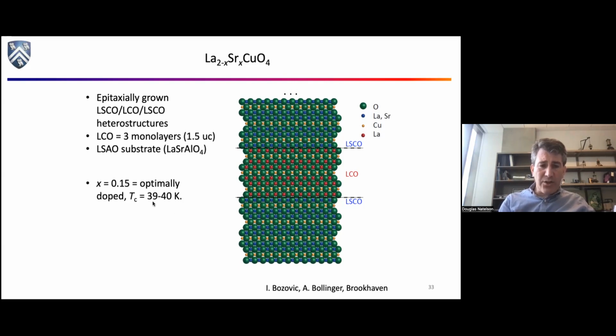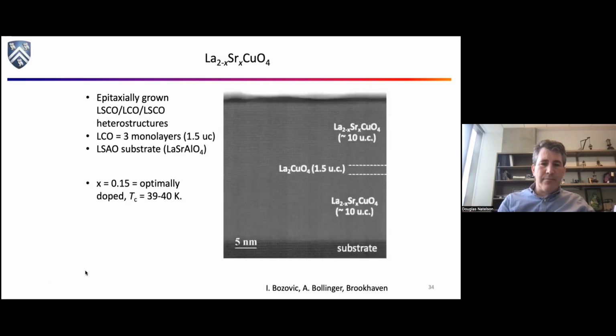And what we're going to do is we're going to look at a bunch of different doping values, a bunch of different values of X here, right? So when X is 0.15, that's about as good as the superconductivity gets in this material at ambient pressure. TC is around 39 Kelvin. That's when it goes superconducting. Okay. Here's an actual cross-sectional